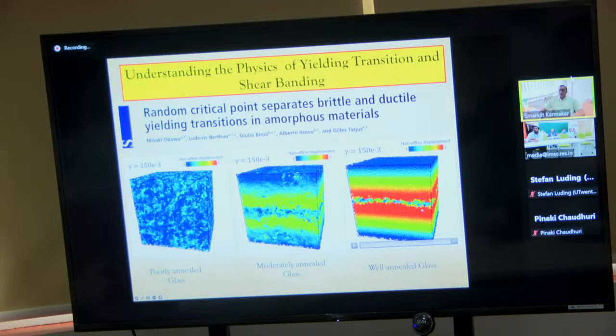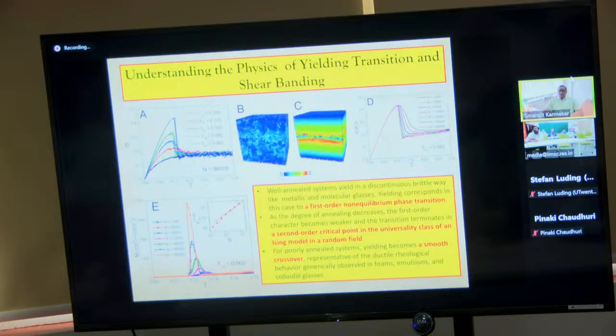So now, even on a computer, one can easily generate shear bands and actually study what leads to such shear band formation. There are interesting proposals by the same group that this shear banding process in ultra stable glasses is a kind of first order non-equilibrium phase transition, which has been debated a lot in the literature, and it's not clear what it is.